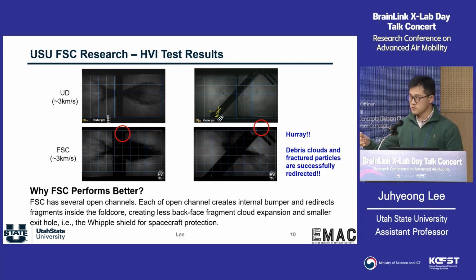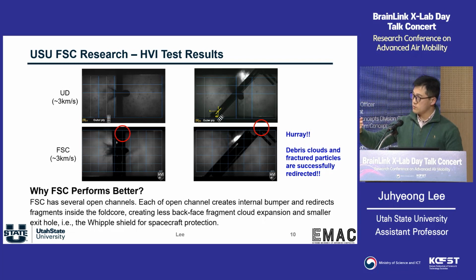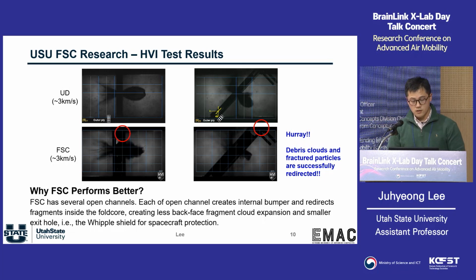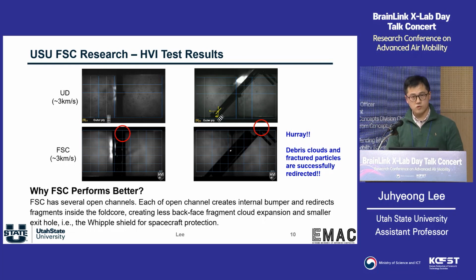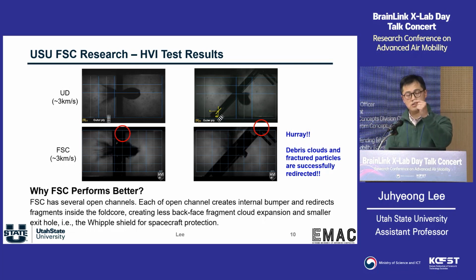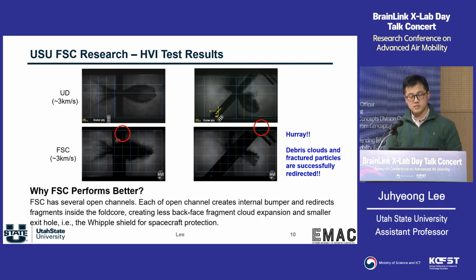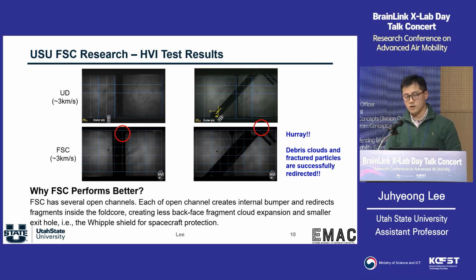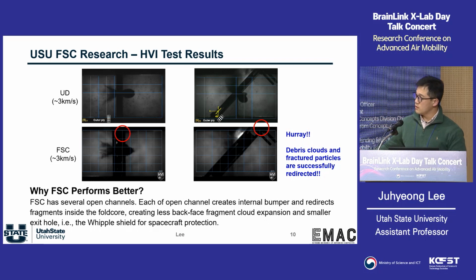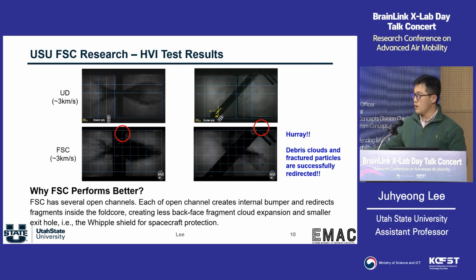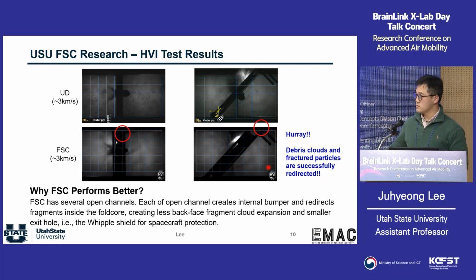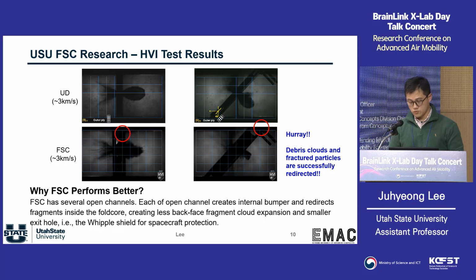So if you're looking at the animation, the right-hand side is the backside, and the left side will be the impact surface. And as I mentioned, the fold core has all kinds of open internal core channels. So when the projectile hits the sandwich panel, there is some debris, a secondary impact due to the fracture of the projectile. However, all kinds of debris fracture in the middle section can be redirected inside. That means any component behind this impact side will be safer. That's why we see very positive results after this super expensive testing.